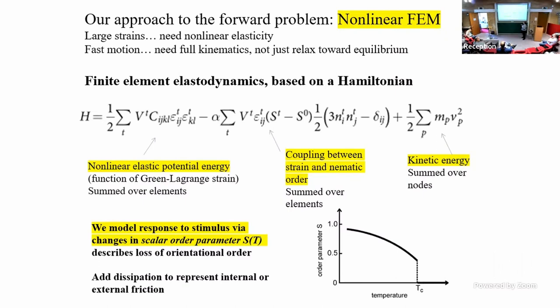Okay. So what is this middle term? Okay, if there's a liquid crystal expert in the room, you will recognize this as a scalar order parameter times this thing. That's the Q_ij tensor that describes nematic order. If that's not familiar to you, you can not worry about it. But the key issue is that it couples with the strain. So Q_ij epsilon_ij, this is actually a form I think that was proposed by de Gennes. And then the key issue here is that the scalar order parameter is, for instance, temperature dependent, that's how the stimulus happens. So when you change the temperature, the scalar order parameter goes down.